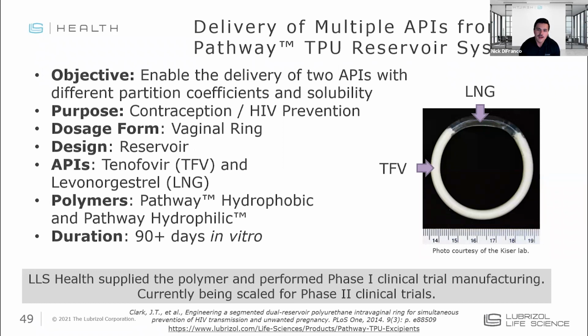What you see in the bottom 3/4, the white portion of the ring, is actually a Pathway thermoplastic polyurethane tube that's loaded with tenofovir paste. And this was the way to incorporate tenofovir to get it to release at the desired rate. It's essentially a core sheath system that utilized a very unique way of incorporating the drug into the tube. And the Pathway TPU was selected to control that release rate to the desired level for tenofovir.